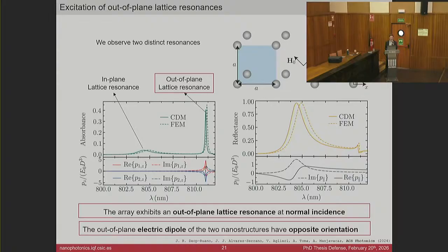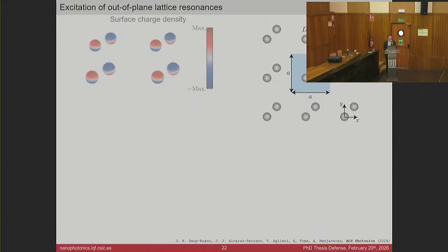That, again, is really simple. Every nanostructure is just an electric and a magnetic dipole, but still we obtain a really good match with full wave simulations. We can also use these full wave simulations for studying the surface charge density, and see that the oscillation of the surface charge density corresponds with an out-of-plane oscillation, and we can also see here the opposite orientation of the two dipoles.